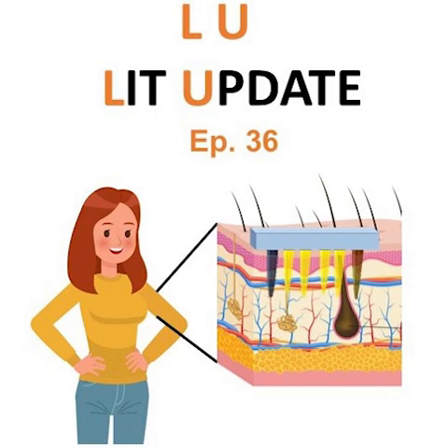Now, before testing it on humans, we have to make sure that it's safe. Of course, yeah. So they tested the safety through both cell and mice studies. They incubated the microneedles with osteoblasts and fibroblasts for 24 hours and found no significant change in its viability compared to the control. And in the mice study, the mice organs and immune inflammatory responses didn't show any adverse effects to the body, even after 7 days of wearing the microneedles. Oh, that's awesome. You can wear it for a week. Really good to know.